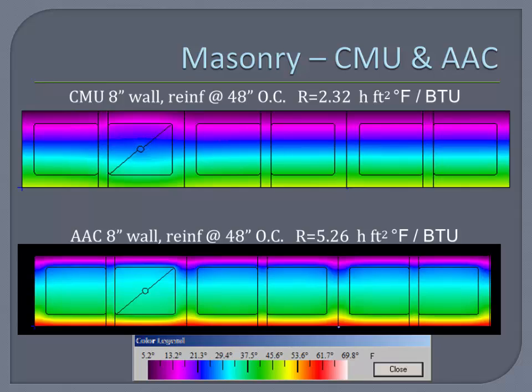And in essence, the carbon payback was just a couple years, if I can put it in those terms, in that the carbon initially for the CMU was less. It's more locally made, even though it's a Portland cement product. The AAC is only about 20% more in the manufacturing as far as carbon. But because of the insulative differences there, the difference turned out to be a payback in carbon of just 2 or 3 years.